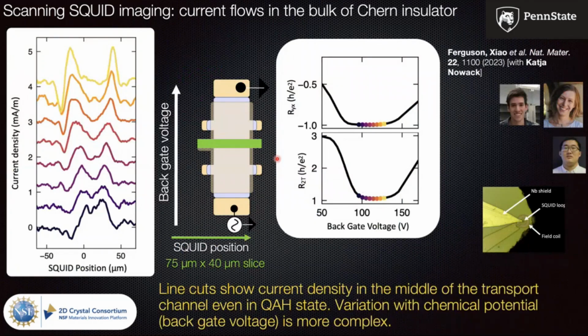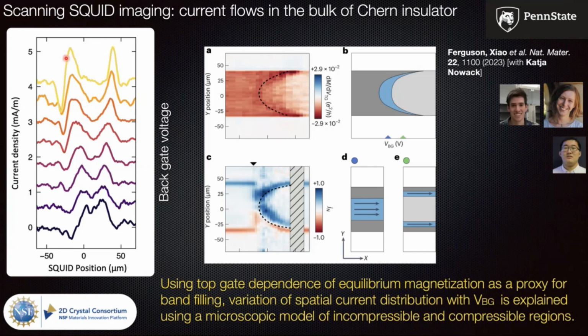If you take line cuts of the current distribution and how it changes as a function of the chemical potential as you backgate your device, you find that these current flows take on different kinds of patterns. In some region of the chemical potential, the current is flowing everywhere in the sample, and on the other hand, if you go further away, like in the top plots over here, you see that it's splitting up into edge-like flows. And Matt Ferguson, the student, did a beautiful job using the top gate dependence of the equilibrium magnetization to argue that this is really mapping out the way the compressible and incompressible regions develop as you take your chemical potential from near the valence band up into the conduction band, through that magnetic gap.